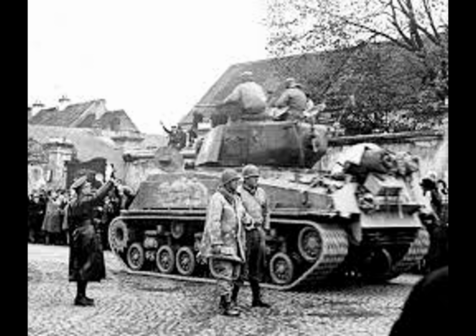Post-war analysis of German armour confirmed what wartime testing had suggested. German face-hardened armour, with its extremely hard surface layer and softer core, performed excellently against blunt-nosed projectiles that failed to penetrate the hard face. But Allied armour-piercing rounds increasingly used caps, soft steel tips that deformed on impact and prevented shattering of the projectile before penetration could occur.